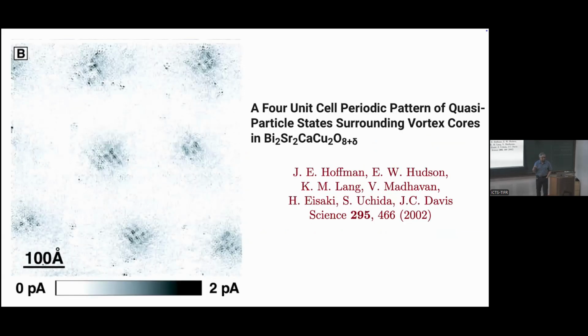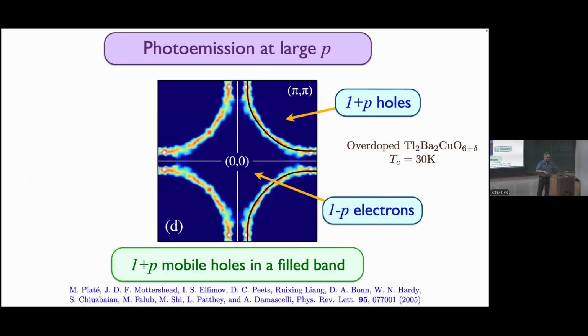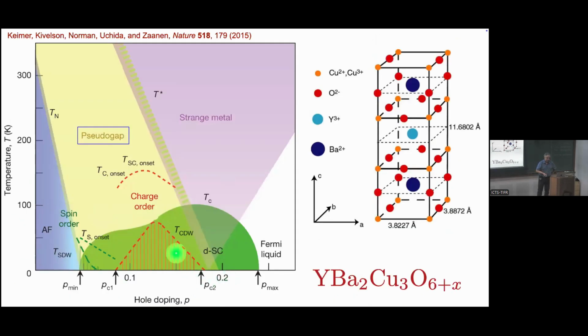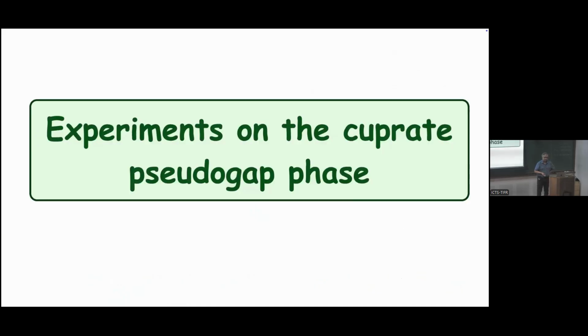Another characteristic of the pseudogap, which if I have time I'll also discuss, is that if you go to very low temperatures and look at the superconducting state, then out here this looks, for all the world, just like a simple BCS superconductor, except the pairing is anisotropic. And as you go across in low magnetic fields, nothing much seems to change. So even here, we expect it to be an ordinary BCS superconductor. But there's one clear difference between the overdoped superconductor and the underdoped side, and that has to do with the structure of the core of the vortex.